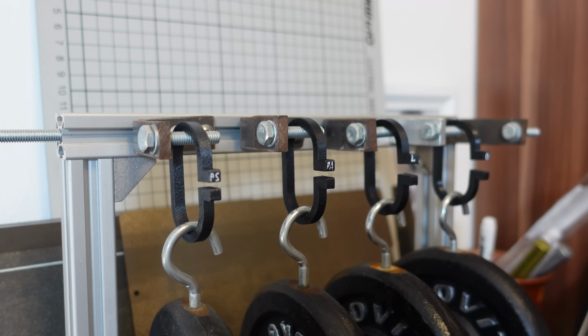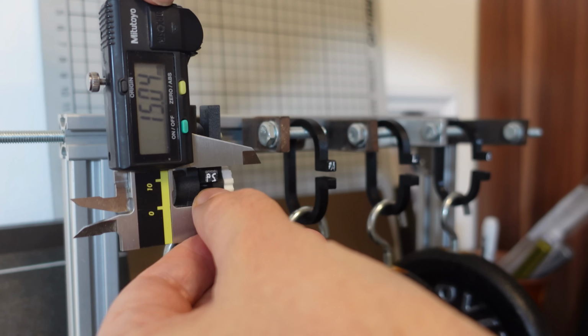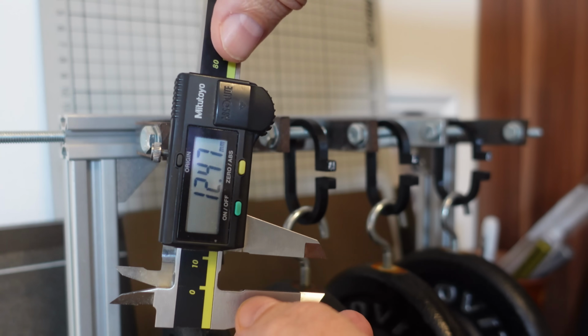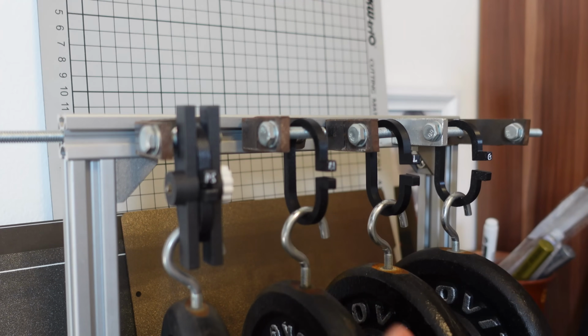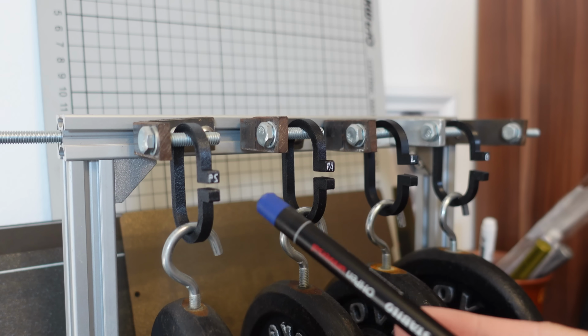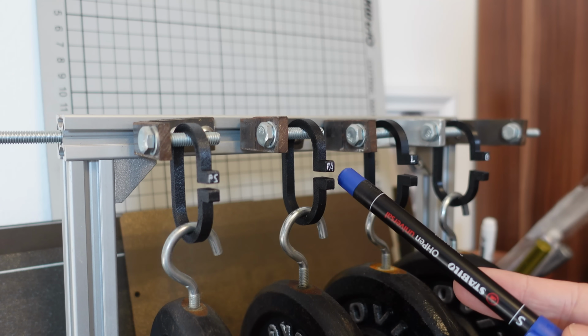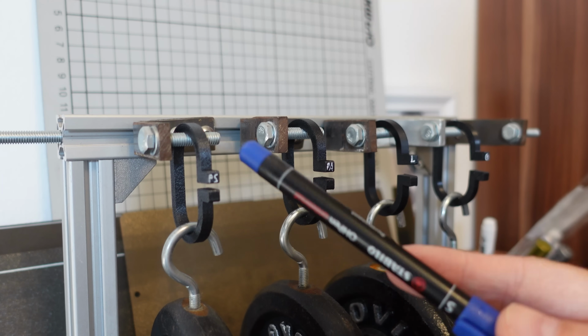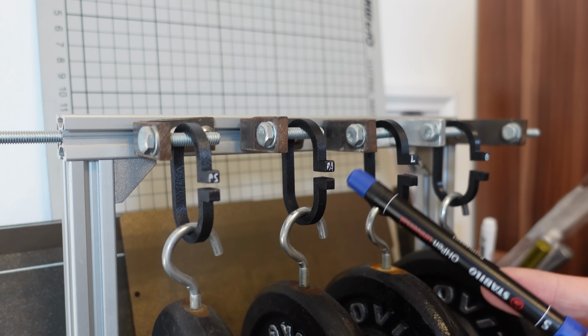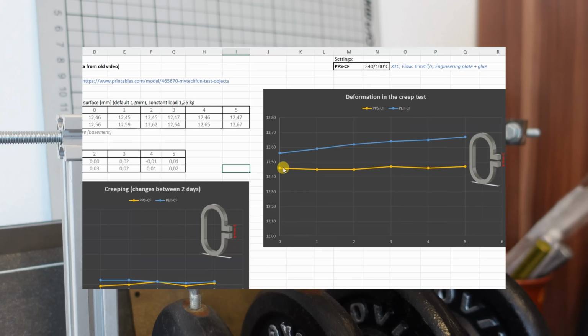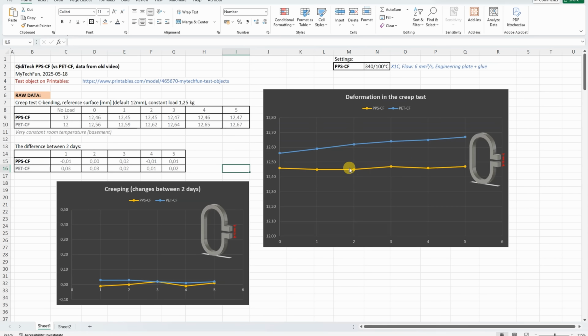This is day 5, time for the last measuring. Wow, almost no additional deformation on this PPS-CF. And just an interesting information, it had a bigger initial deformation than this PET-CF, but absolutely no creeping, and here now the deformation is bigger than the PPS-CF. Both materials are good against the creeping, but this PPS-CF, not only that it has small deformation compared to the PET-CF, but look at these changes. This is just an inaccuracy in the measuring, but basically no kind of creeping during these 5 days.